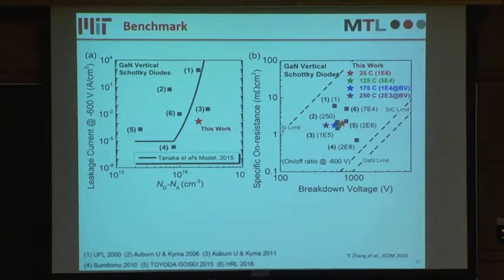But by having all these TMBS and field ring structures, we're able to lower the leakage current by several orders of magnitude and make this leakage current comparable to devices with a 10 to the 15 level donor concentration.